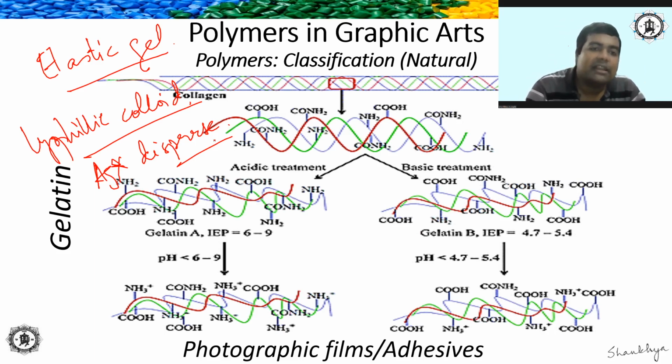To keep the silver halide dispersed uniformly throughout the film, gelatin is used as a protective colloid, or the lyophilic colloid, which encapsulates the lyophobic colloid and prevents any electrolyte from attacking the lyophobic colloid and neutralizing it, and hence prevents its coagulation. That is the importance of gelatin in our industry.